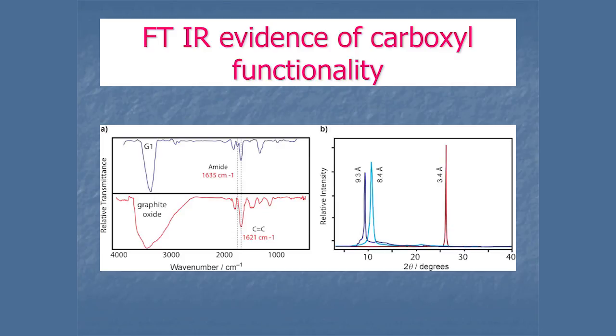Therefore, we have cloned the glucose oxidase, and so we use the cloned recombinant glucose oxidase. We also have developed by protein engineering methods a very large number of mutants that can interface with a single layer graphene very effectively. Then we use Fourier transform infrared and Raman in the signature regions: amide 1 and amide 2 in infrared, and amide 1 and amide 3, the carboxyl stretching region, will show perturbations that will indicate that the enzyme has been successfully bound, and is retained in that state. Otherwise, it is useless. FTIR gives evidence of carboxyl functionality.